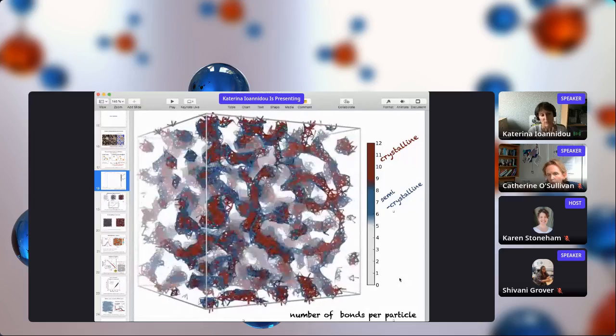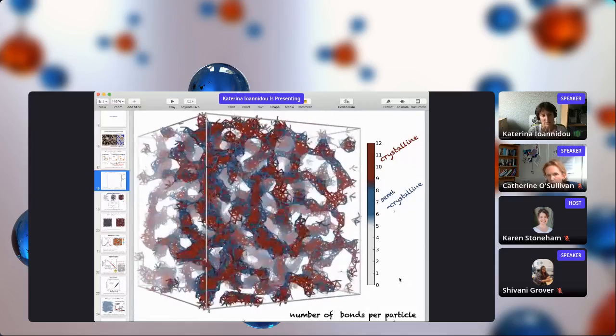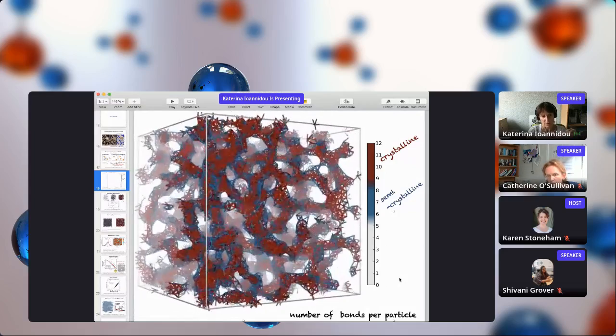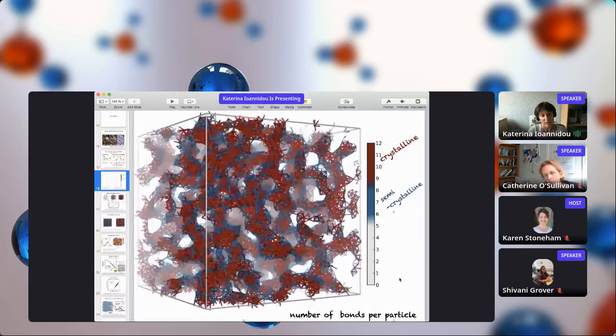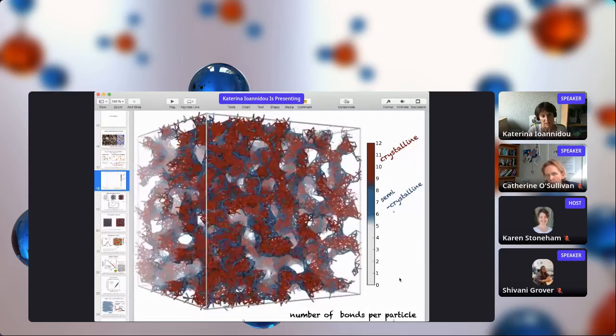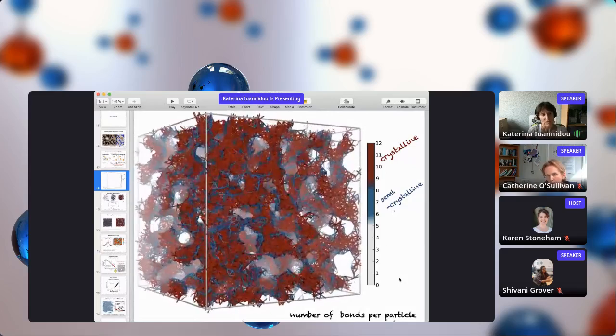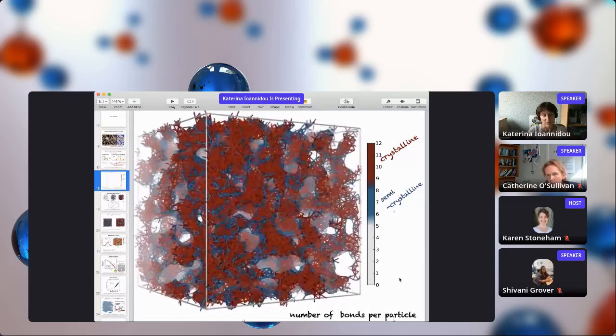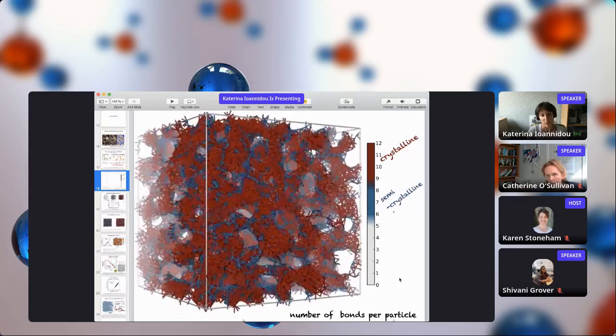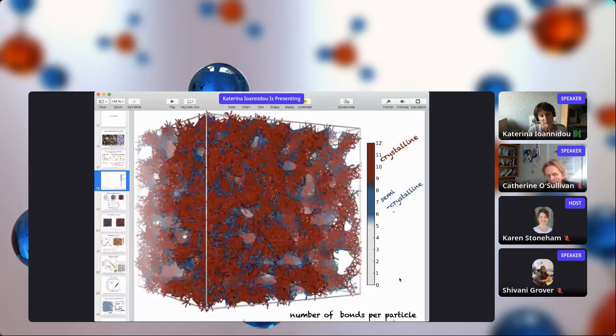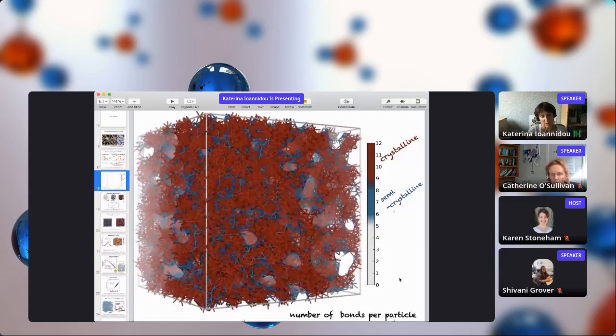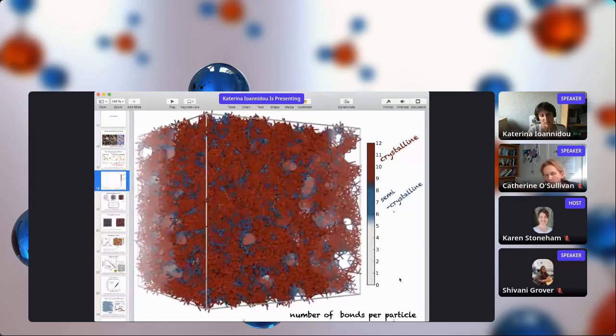We start from a system that has clusters growing in an elongated fashion, and these elongated clusters form a gel network. On top of this gel network, we have the creation of a porous solid. Most of the material here, as you see, is red, so it will be crystalline-like. This is because the simulations are done with monodispersed particles.